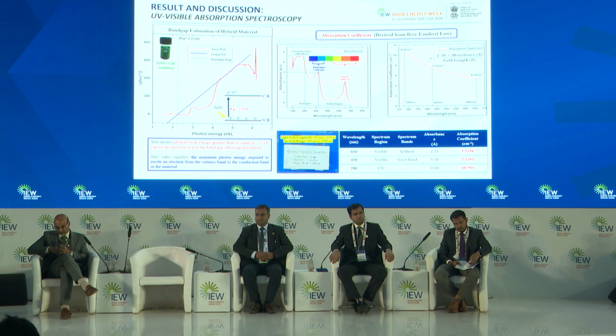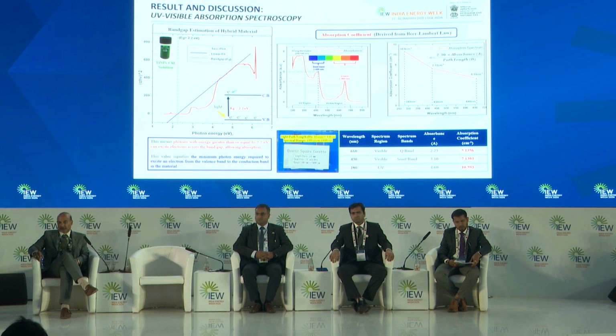UV-visible was important because we want to check how much light harvesting capacity this hybrid material had. From this UV-visible spectroscopy we can see that there was a tremendous shift of this hybrid material toward the visible spectrum, that is from 300 to 700 nanometer. So it had this light absorption capacity, and it was good for solar fabrication.